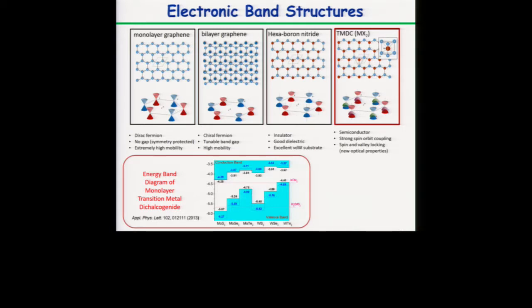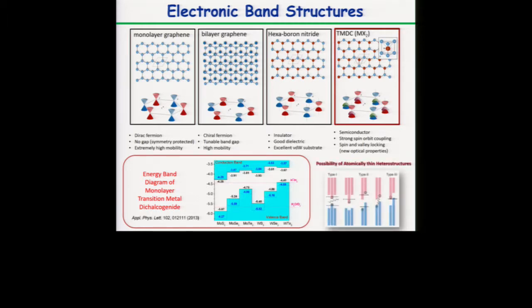And this is the band diagram of each of these TMDCs. As I said, the band gap is around 2 electron volts. The band alignment is very different between them, so we can choose, depending on where we want the band alignment to start and what band gap we need, among each of these TMDCs. Okay, as I said, we can form different types of heterostructures. It can be a type 1 heterostructure, where we put two elements, one of them with a bigger gap than the other, and the alignment is like a contained heterostructure. We can make a type 2, where they are shifted with respect to each other, or we can even make a type 3, which is even more shifted. So with this, using these building blocks.